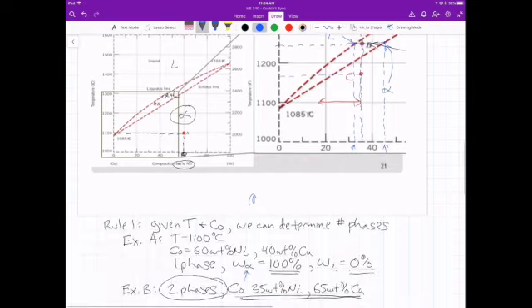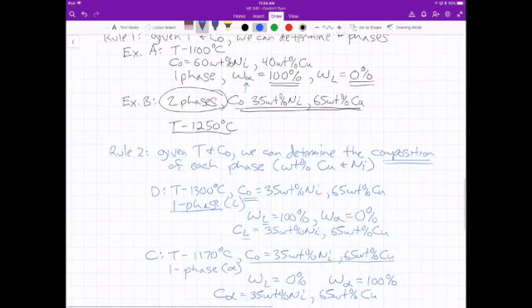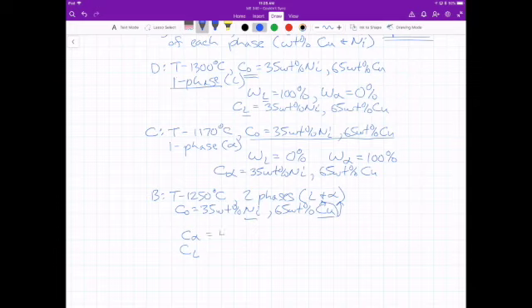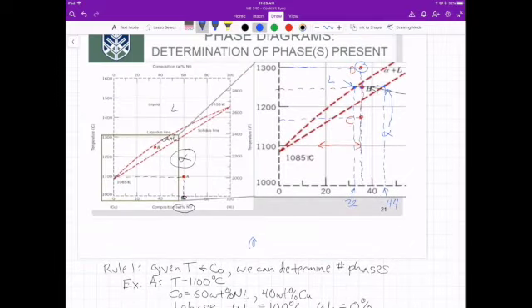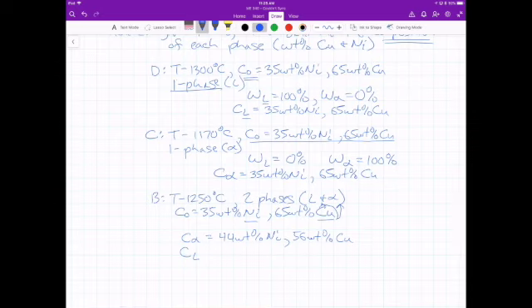So what would those values be? Looks like about 32 here, and this looks like about 45. Let's say 44. So how would I write that? The solid phase was 44, so 44 weight percent nickel. How much copper do we have? 100 minus 44, 56 weight percent copper. For the liquid line, we go to the left and then down, we get 32 weight percent nickel. How much copper do we have? 68 weight percent copper.